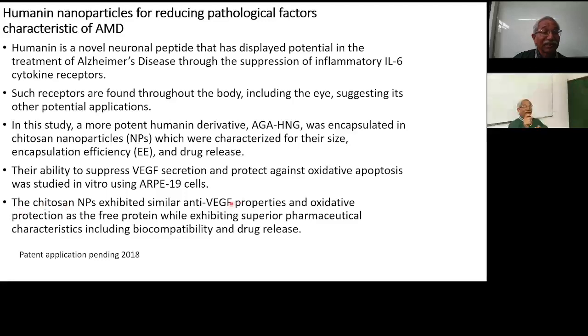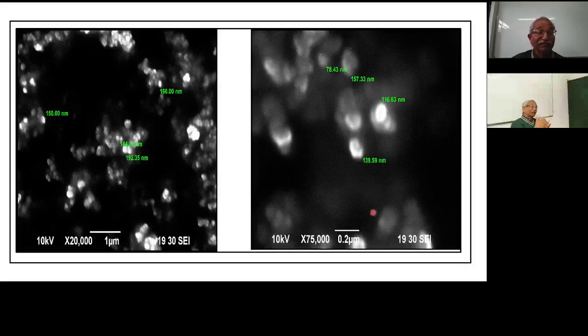And we created chitosan nanoparticles with anti-VEGF properties and oxidative protection of free protein, while exhibiting superior functional characteristics, biodegradability, biocompatibility and drug release. A patent application is still pending for humanin. Now in place of PLGA-PEG, we used chitosan as a polymer. It's a natural polymer, so it is more biocompatible with the body. So we created and explored that, and the particle sizes were like 150 nanometer and 160. So the average particle size was much lower than 200 nanometer, because that was what we wanted.